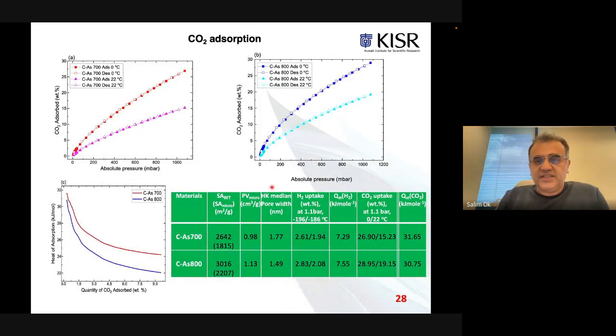We looked at carbon dioxide uptake, or carbon dioxide adsorption. Again, as you can see here, especially in the case of the carbonized asphaltenes at 700 and 800 degrees Celsius, carbon dioxide uptake reaches up to 26 or 28 weight percent at 1.1 bar. But when we go to slightly higher temperatures, this carbon dioxide uptake started decreasing. Still, we got pretty nice, promising results.